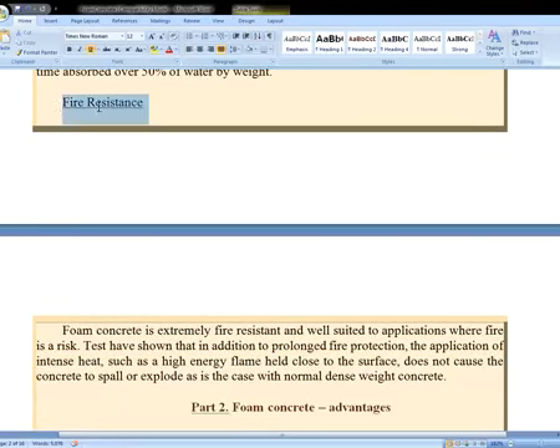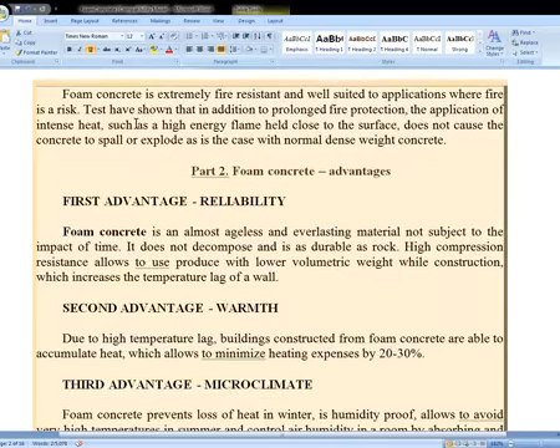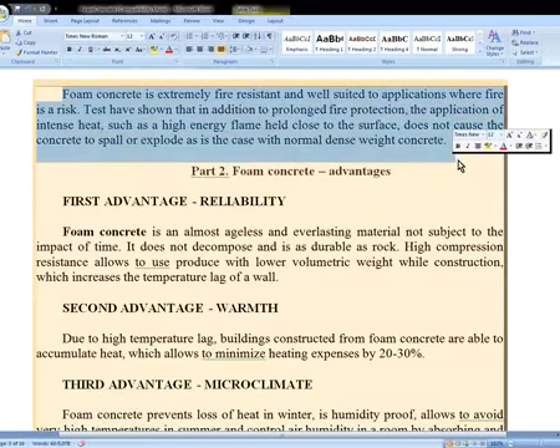Fire resistance. How is it with fire, what will it say, how shall it talk to fire. Now foam concrete is extremely fire resistant. It resists fire well. Foam concrete is extremely fire resistant and well suited to applications where fire is at risk. Where there is a fear of fire, if you use this, it is in the interest of that building. Our tests have shown that in addition to prolonged fire protection, application of intense heat such as a high energy flame held close to the surface does not cause concrete to spall or explode as is the case with normal dense weight.